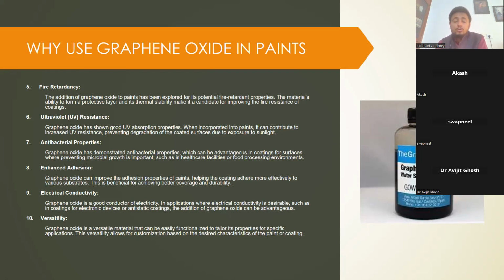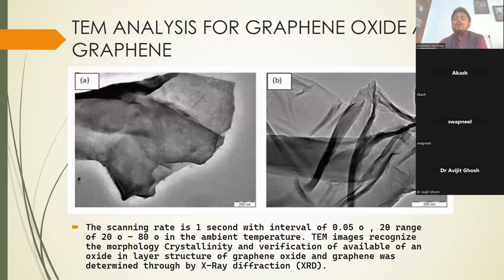People are using graphene for anti-fouling polymer nanocomposites, like for overhead tanks where water is kept for a long time, so algae and fungi can start growing. So it is used for avoiding that. Enhanced adhesion you get, because it plays with the surface energy of the substrate. Because of that, you get high adhesion, you get excellent electrical conductivity, and it is a very versatile material.